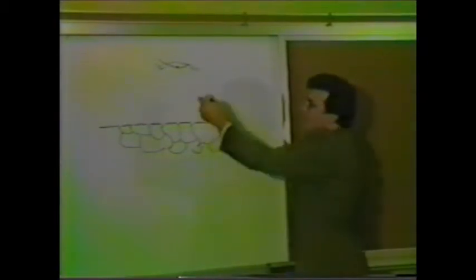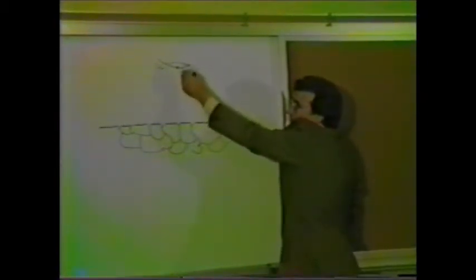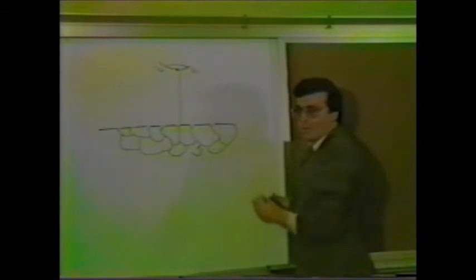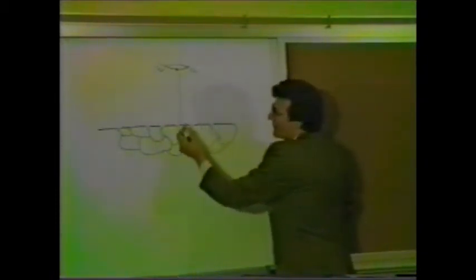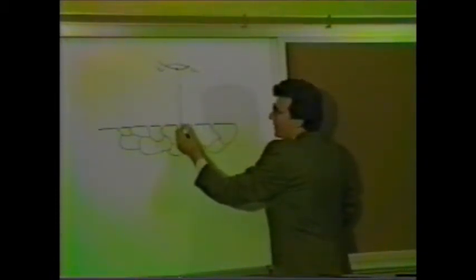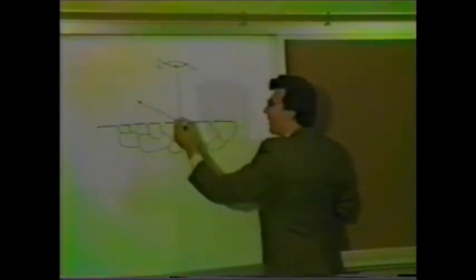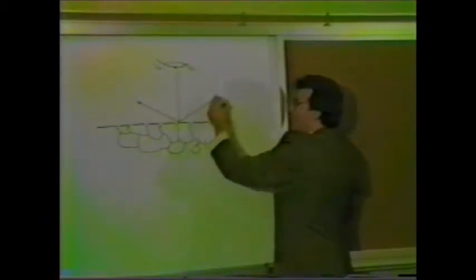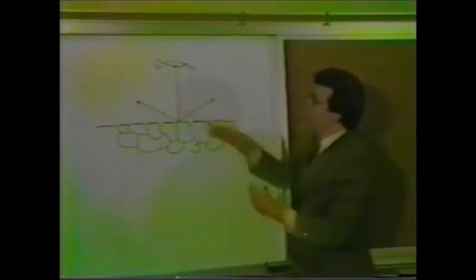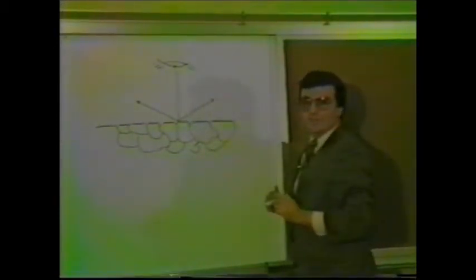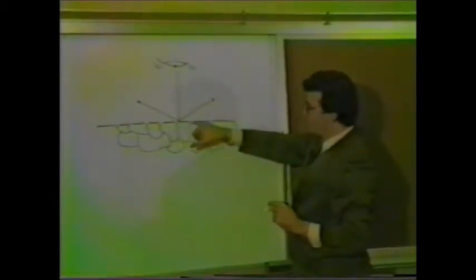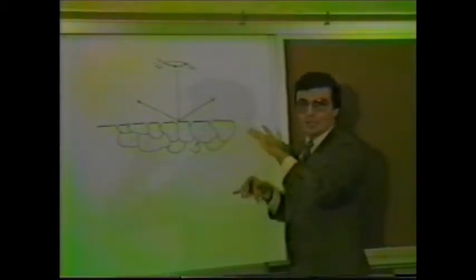Well, what this does, this relief that's put into the steel, now as the microscope or your eyeball looks downward, any area that is still flat gets the light reflected straight back up, and that area looks white. But when the light, as it scans across here, intersects an area where the grains are, it'll bounce off to some other angle, maybe coming down here and bouncing off here, and this light does not get reflected straight back up into the microscope, and the areas where the grain boundaries are appear as dark lines.